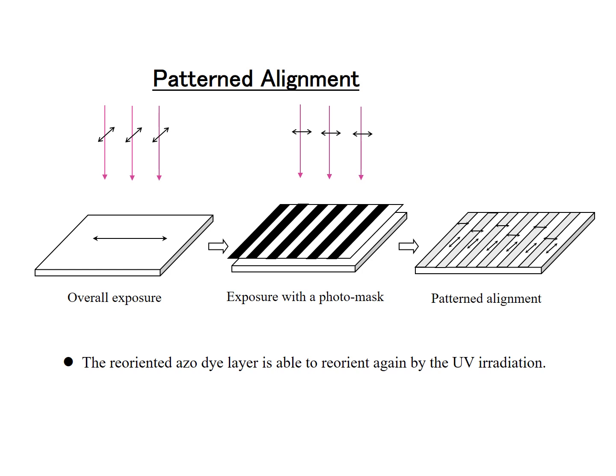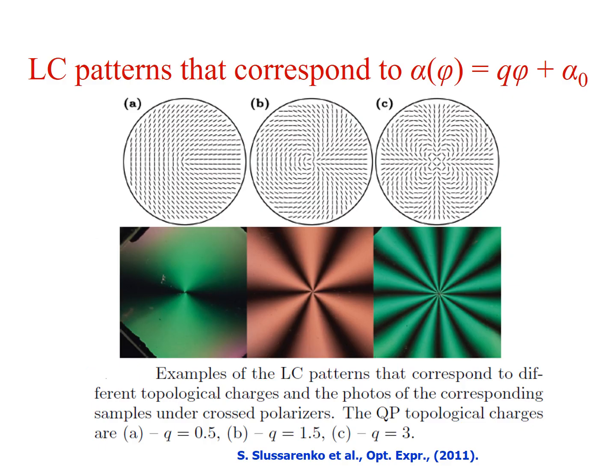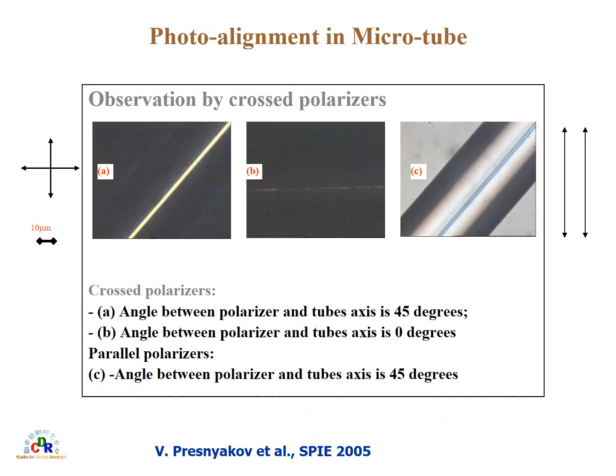Also, we can write a lot of different diffraction gratings and photonic elements using photoaligned azo dye layers. By making a double exposure with the polarization changed by 90 degrees, you can write a patterned azo dye alignment. Or if you expose and rotate the plates, you can make so-called Q plates, which we published in 2011. These Q plates can be efficiently used for optical data. We can also get photoalignment in microtubes and fibers, where the usual rubbing technology is not possible.